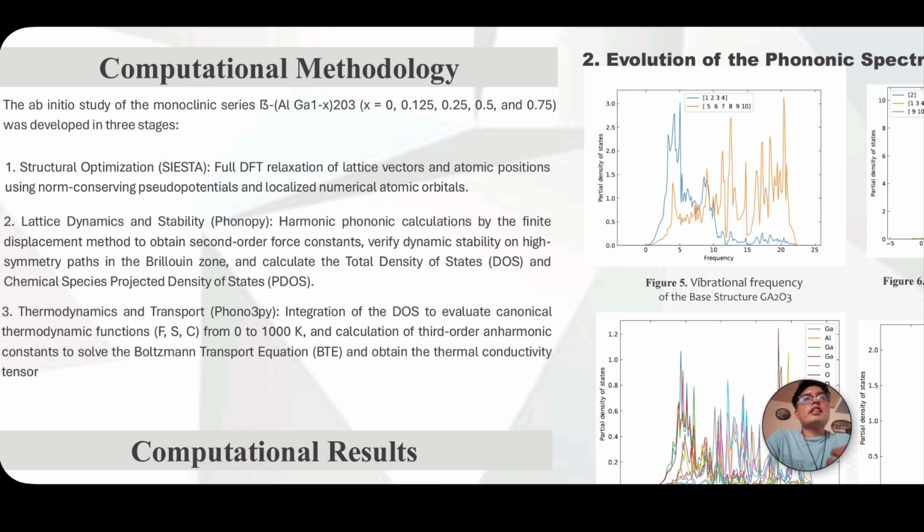Finally, for the third stage, thermodynamics and transport with Phono3py, we evaluate the thermodynamic functionals between 0 and 1000 Kelvin and obtain the third order anharmonic constants needed to calculate the thermal conductivity tensors.